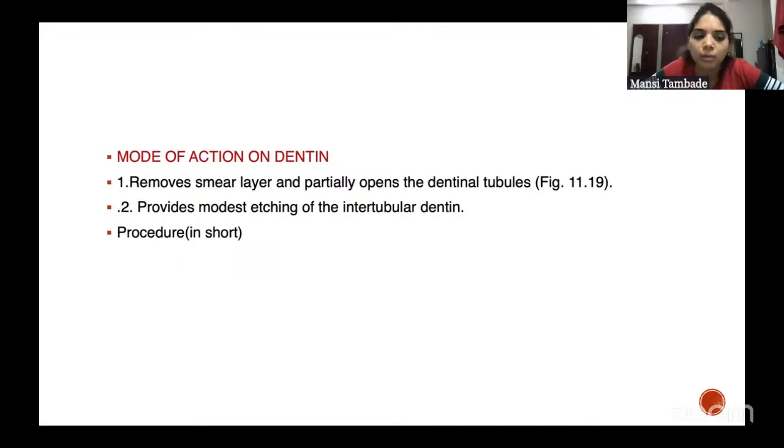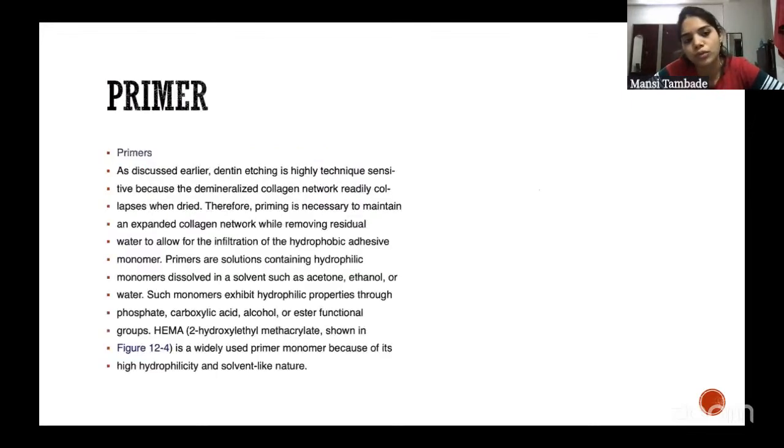Okay, the first one is to take the tooth of interest, that is, the area you're going to do. You have to clean it with water, then dry the tooth, then you need to apply the etchant on the surface. You need to brush it for like 15 to 30 seconds. Basically 15 seconds is the time we use. Then you need to wash it off with water, then again dry it, but you should not over dry it. That will cause consequences, which you'll definitely understand while you're reading the whole procedure. And then you need to isolate it for the further process of bonding, that is, the application of the second step, which is the primer, the application of the agent.